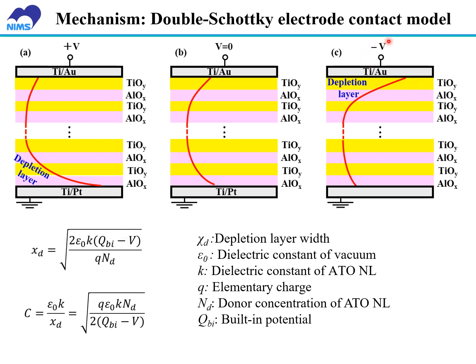On the other hand, when the voltage is negative, the depletion layer width on the surface electrode increased greatly. The K value for the ATO nanolaminate also increased. For both cases, A and C, the depletion layer widths are larger than that with the voltage of 0. In this case, the capacitance for A and C are much larger than B. In other words, with the increasing of voltage from 0 to 5 or from 0 to minus 5 volts, the capacitance decreased greatly. Therefore, this is in good agreement with our experimental measurement result.